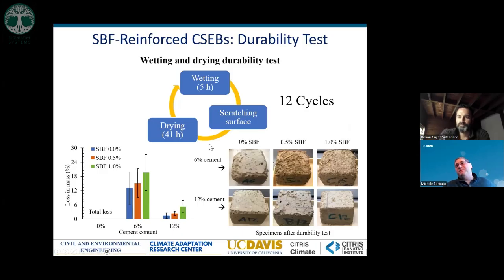A thing we were worried about was the effect of fibers on the durability of the material. The reason being, having a lot of fibers inside the material can suck even more water inside, and we were worried about the production of micro cracking inside the materials. Now, we observed a little bit of increase in loss of mass for the increase in fibers. However, the best way to address that is the increase in amount of cement, and we found that with zero cement, fundamentally, it doesn't matter how much fiber you're using, the material disintegrates after 12 cycles of wetting and drying and scratching the surface.